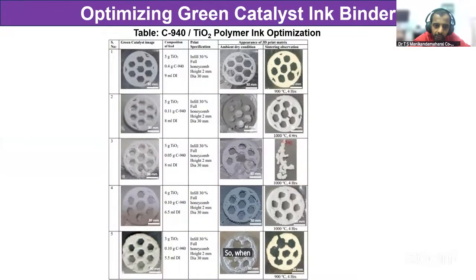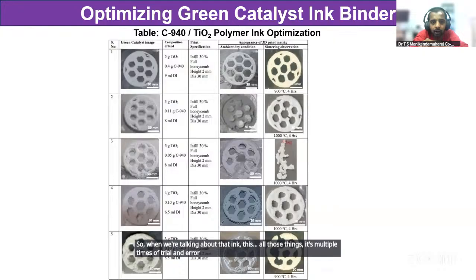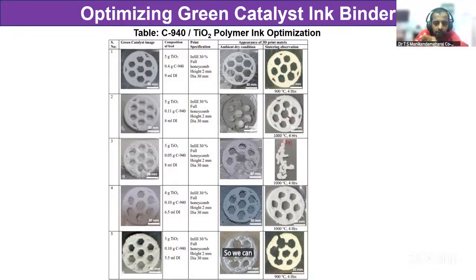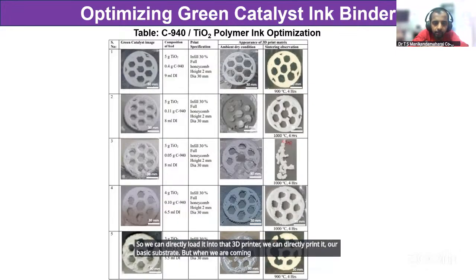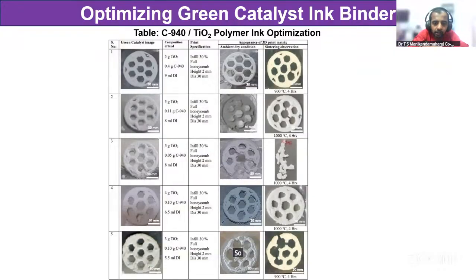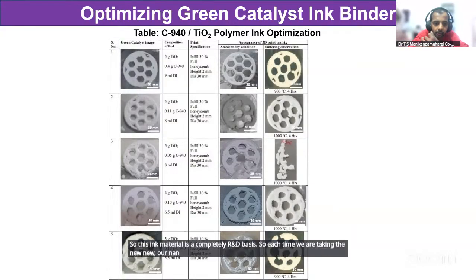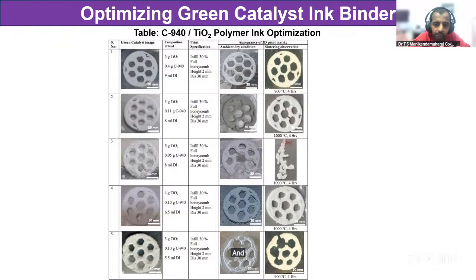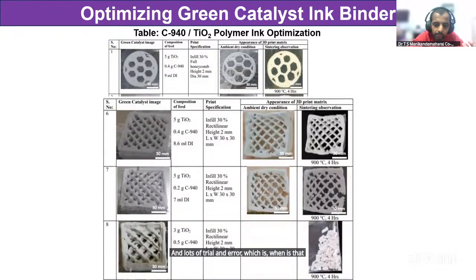When we talk about the ink, it is only through multiple rounds of trial and error that we optimize and find it. Earlier, FDM printing uses thermoplastic material, which is standard optimized stock material, so we can directly load it into the 3D printer and print our basic substrate. But when we come to direct ink writing printing, the ink material is completely R&D based. Each time we take new nanomaterials and bio ink optimization additives, we have to optimize, with lots of trial and error, until we get a better post curing method.